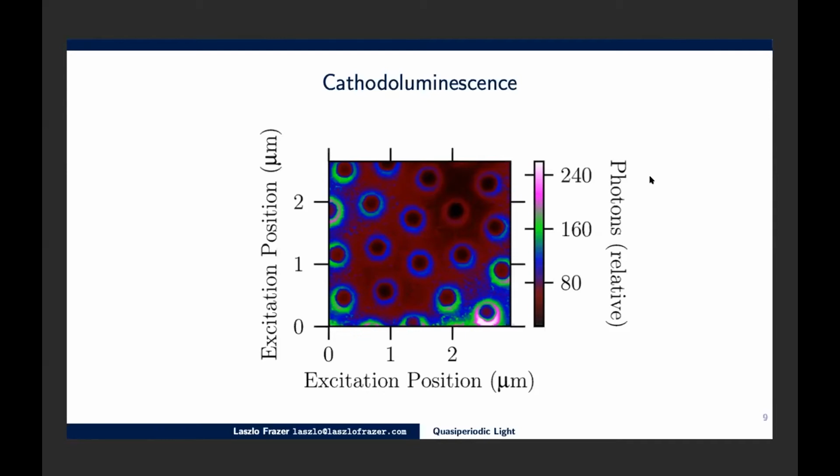Something we don't see here is we don't see any kind of resonant modes, which is something that has been frequently reported in the literature as a property of photonic crystals. And we think the reason for that is probably that those resonant modes are actually further into the infrared than the light emission of this particular photonic crystal. We also don't see any cathodoluminescence of the quantum dots. So we think they're getting quenched somehow. Anybody happens to have an idea for how to see that, that would be very interesting too.